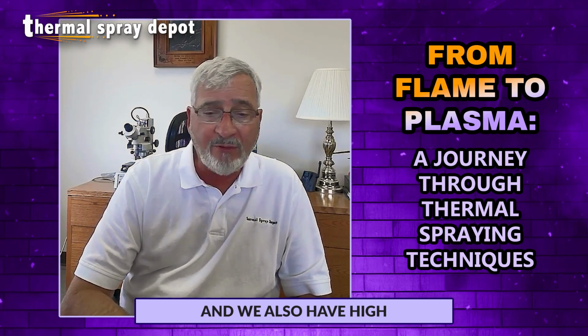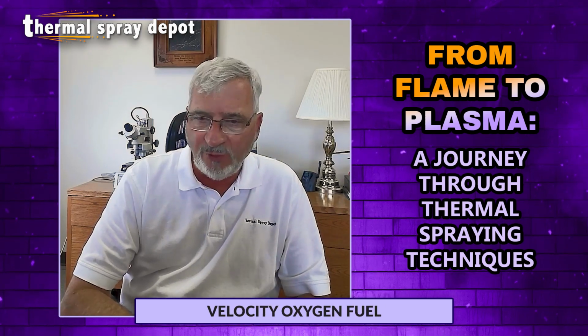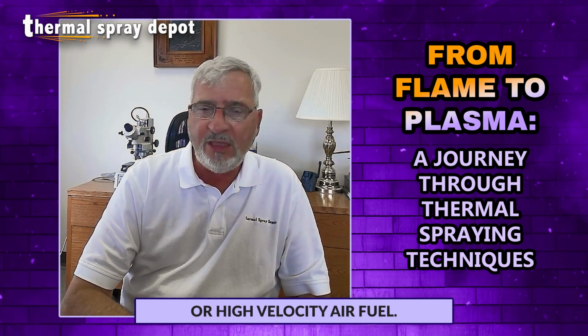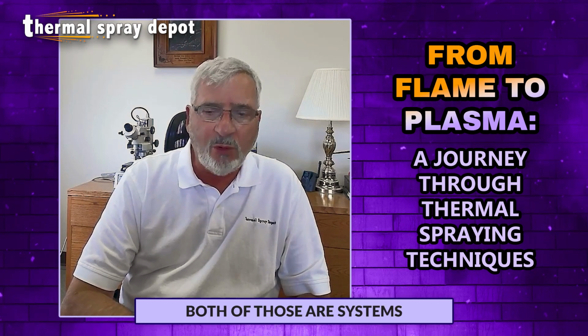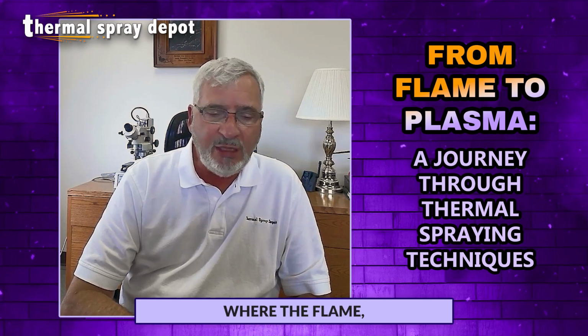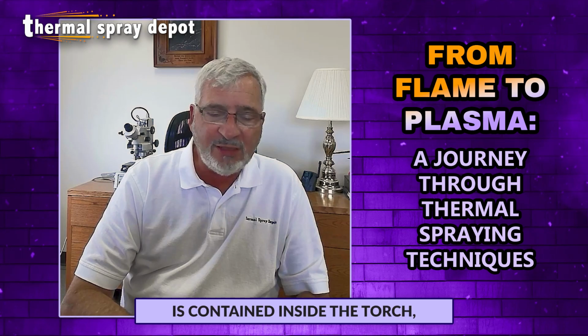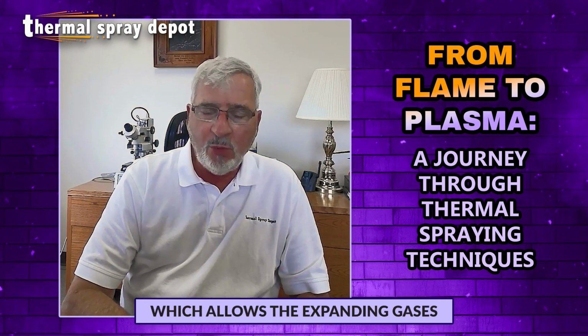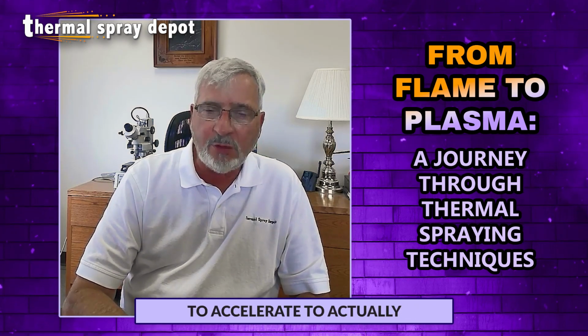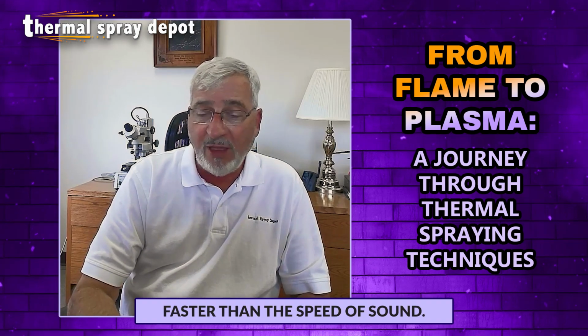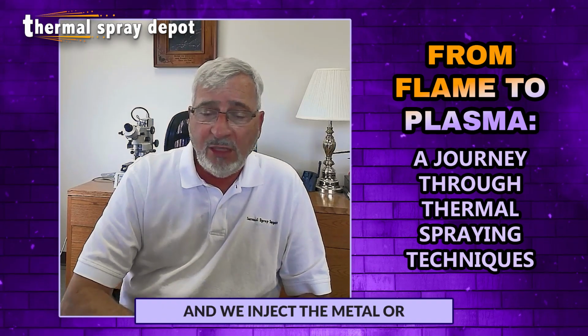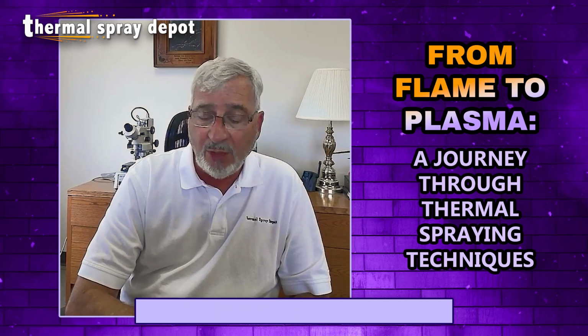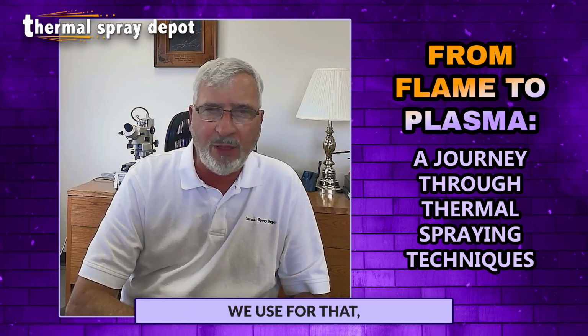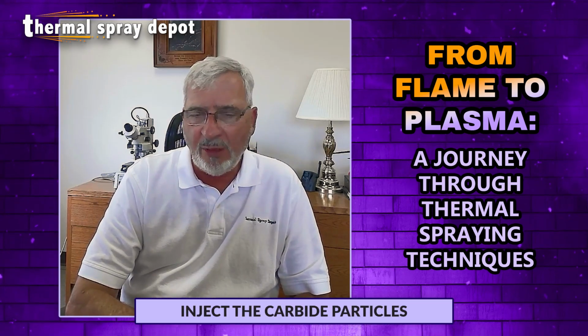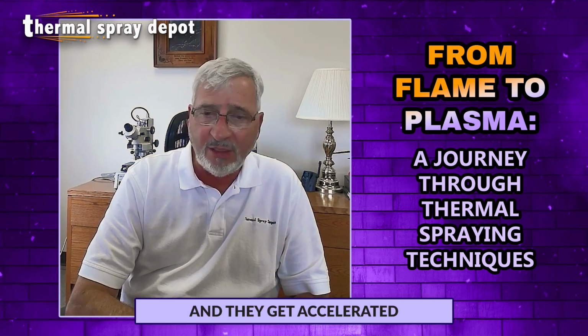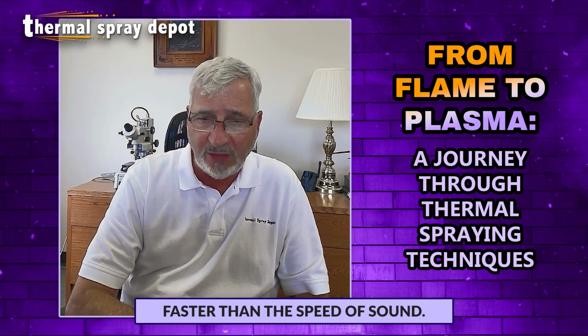Then we also have high velocity oxygen fuel or high velocity air fuel. Both of those are systems where the combustion is contained inside the torch, which allows the expanding gases to accelerate to faster than the speed of sound. And we inject the metal or carbide particles, it's mostly carbide we use for that, into that flame and they get accelerated faster than the speed of sound.